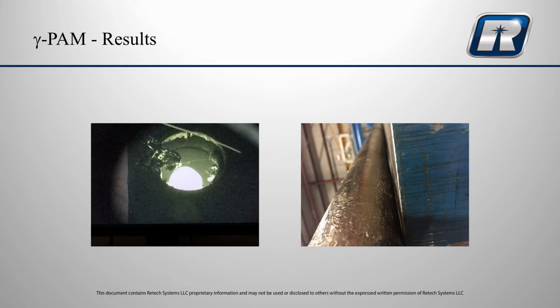Just some of the results here, a brief picture comment. Since we have a little bit of time, the mold with the induction melting is shown on the left. On the top of the mold, off to the left-hand side, is a piece of splash material that came from the hearth. As you can tell, there's minimal influence of that material on the melting performance within the mold. The surface finish of a typical ingot is shown here on the right. The ingot is laid on top of a table, and I took the picture to give it perspective. If it looks kind of funny, it's because the picture is cocked off 90 degrees from how it was originally taken.